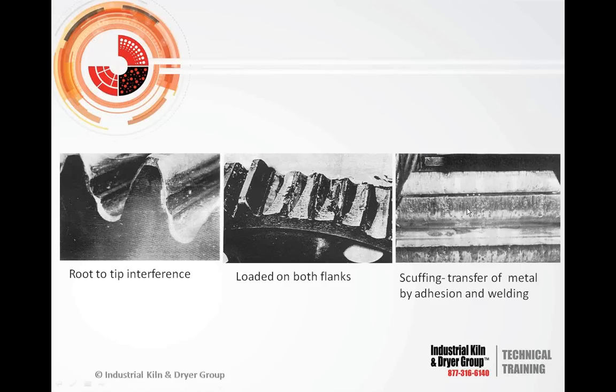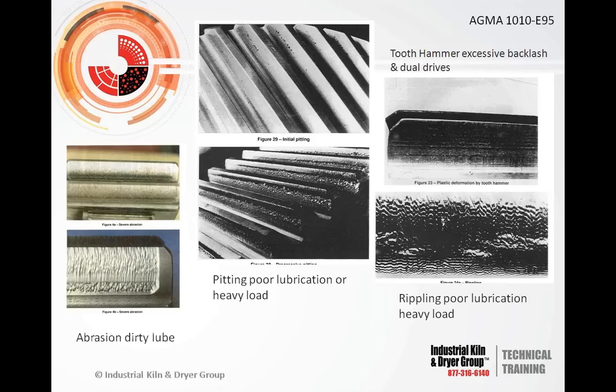Scuffing or transfer adhesion. This is usually a situation where, if you have this type of wear pattern, you have insufficient oil film strength to form a protected rolling contact, and what you're actually getting is the gear and the pinion fusing or welding together, and then you're pulling metal on each time it runs through the contact point.